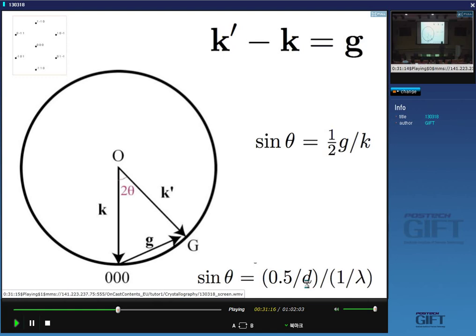So I've drawn a sphere here which has the radius 1 upon lambda. Okay, so k is pointing along the incident beam and k dashed is pointing along the diffracted beam. And g represents the planes which are doing the diffracting, normal to those planes. And this is the origin of the reciprocal lattice. This is a vector representation of the Bragg law. Because just from the geometry here, you can write that k dashed minus g, going in this direction, is the same as k. So this is just a vector equation representing this triangle here. Okay.